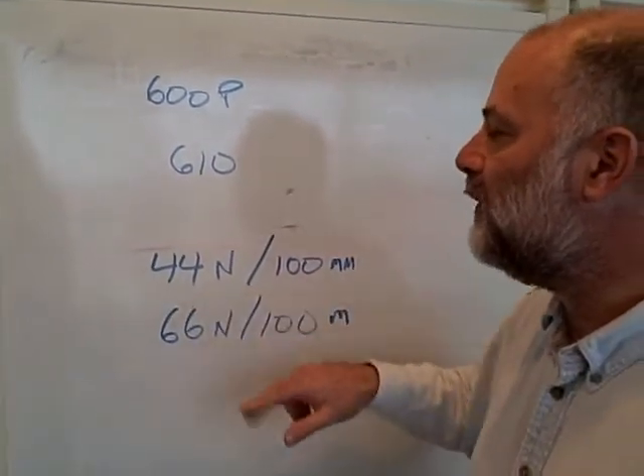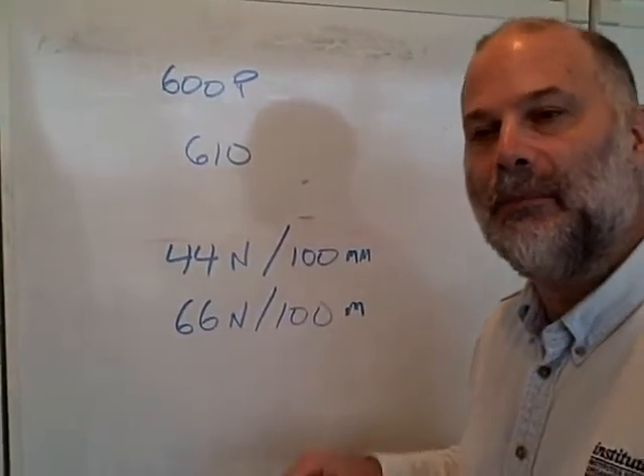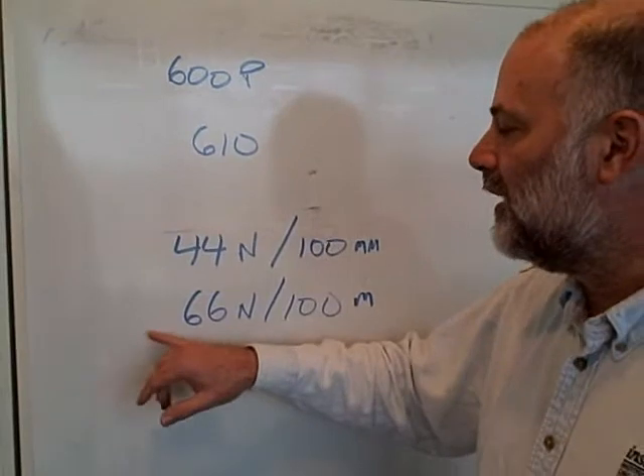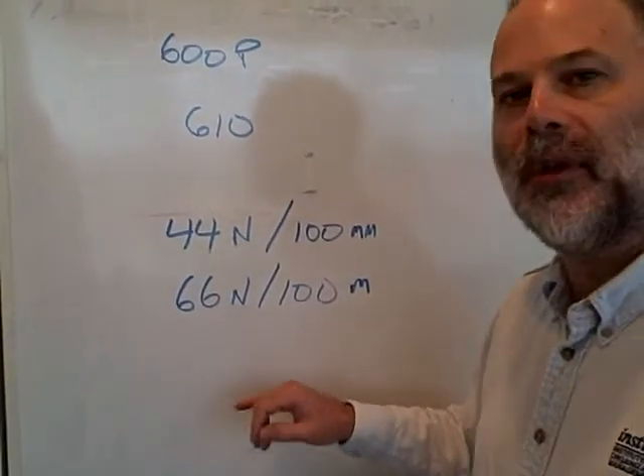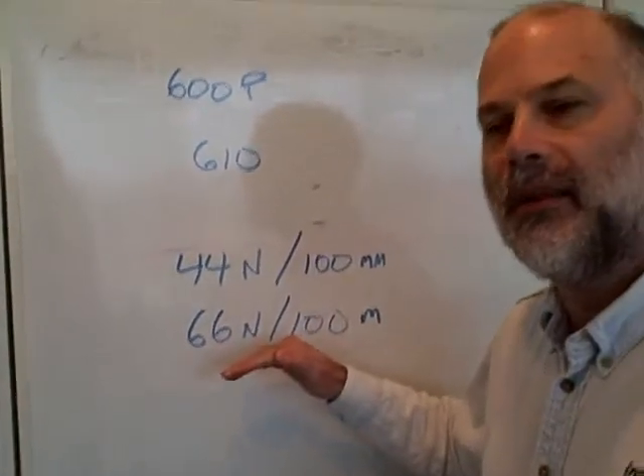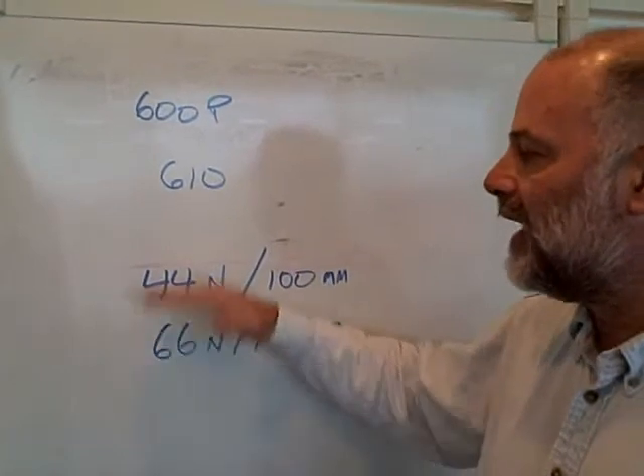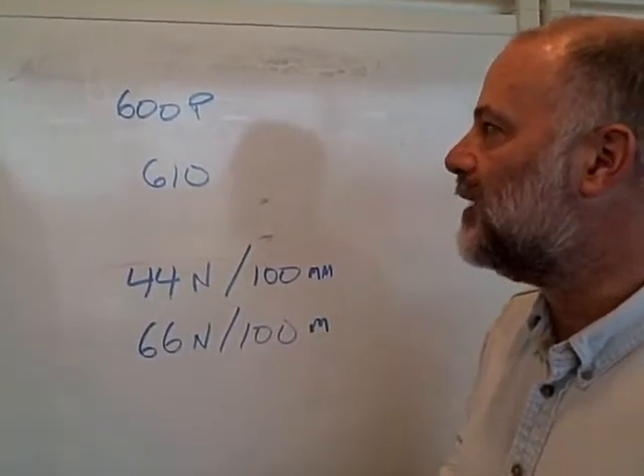As a minimum force, 44 Newtons per 100 millimeters is the minimum adhesion required. The maximum adhesion required is 66 Newtons per 100 millimeters. This is the indication as to any tapes within this range is acceptable for doing the tape test.